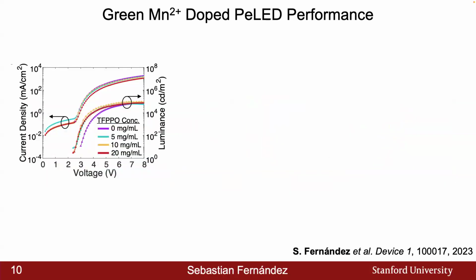Now, focusing on the champion efficiency devices within this study, we saw that all these devices have a turn-on voltage of around 2 to 3 volts, which is really quite good because it implies that it's a very well-engineered device because we're very close to the optical band gap of the perovskite active material, as well as reaching maximum luminances of around 100,000 candela per meter squared. Now, while not shown here, within the study, we also measured champion brightness devices, which were as high as 128,000 candela per meter squared, which were at the time one of the highest among the reported perovskite LED literature.